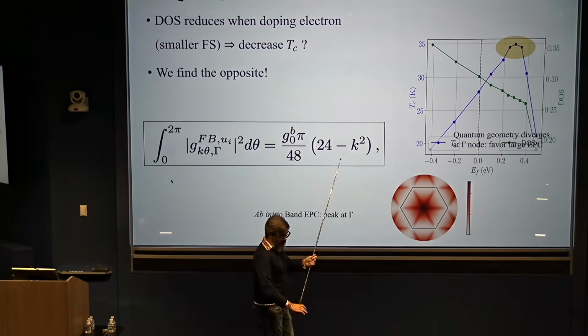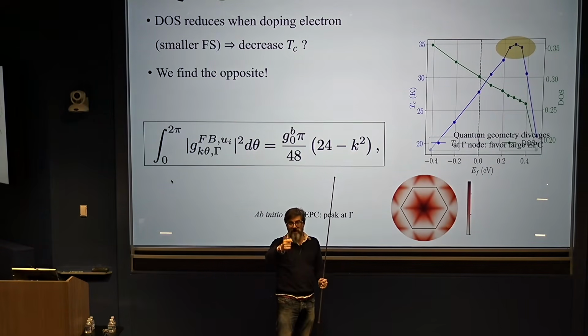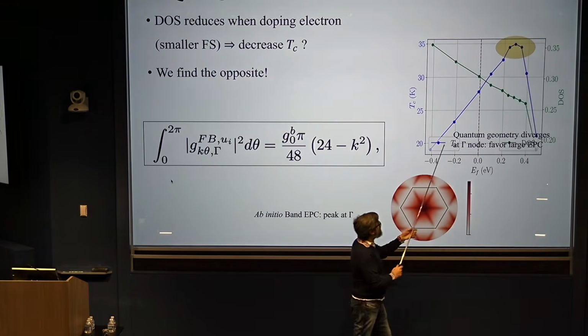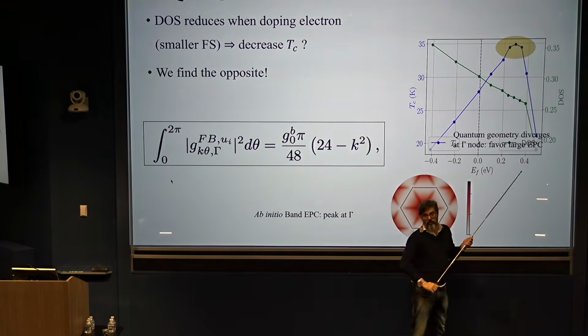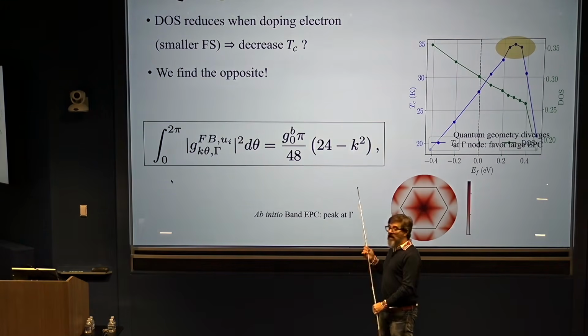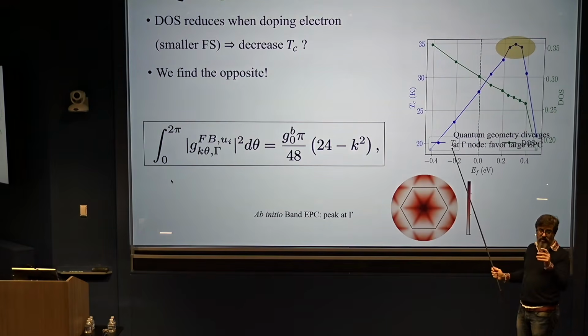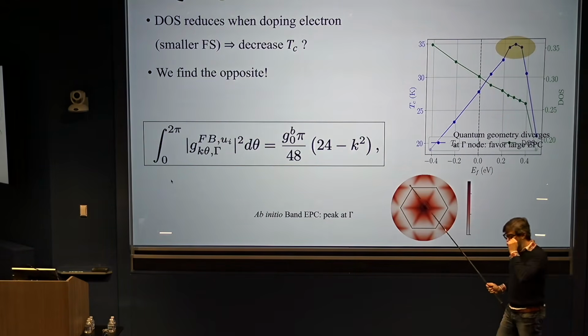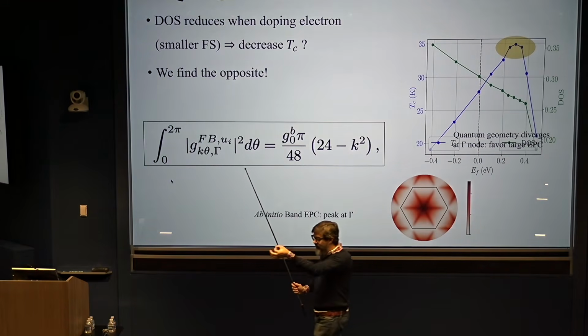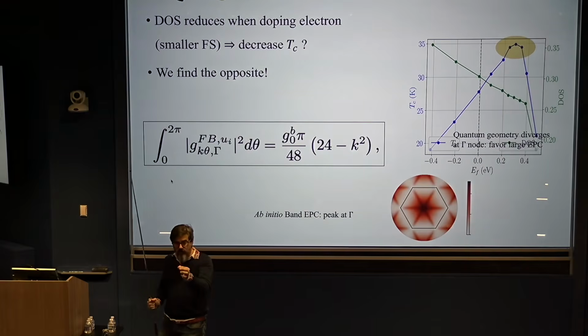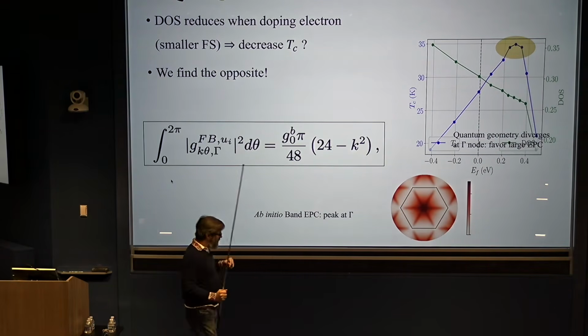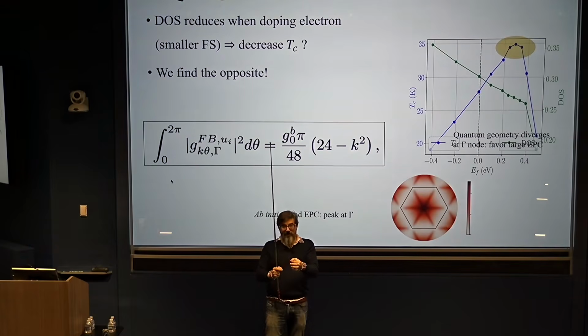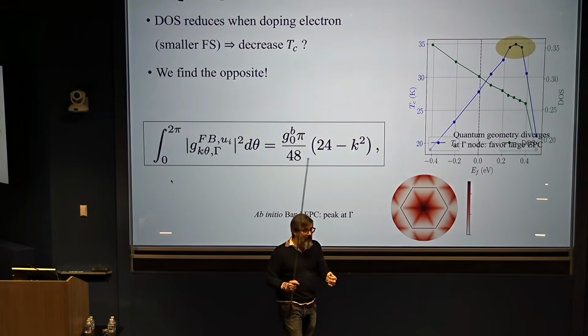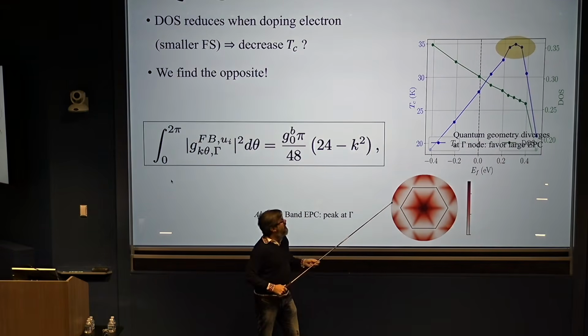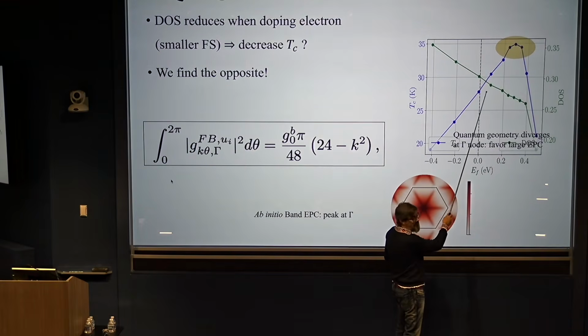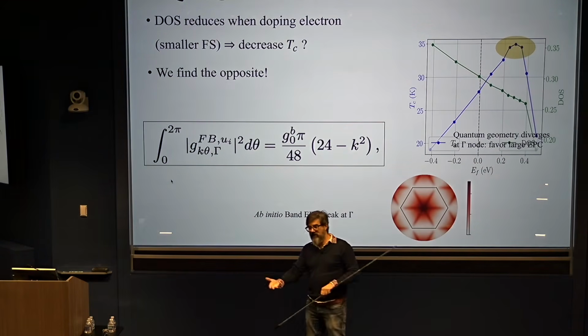What happens is you add electrons to a system, you make the Fermi surface smaller, you lose density of states, you expect Tc to go down. Tc actually still increases up to here, and then it goes down, of course, when you lose all the sp2 Fermi surfaces. And that, we claim, is a pure quantum geometric effect, because the double vortex that I showed you in the wave function at the gamma point has quantum geometry, because the wave functions change as a function of k, and the quantum geometry gets larger as you go to the degeneracy point. And because it gets larger towards the degeneracy point, for a region of parameter space, it's able to overcompensate the decrease in density of states.